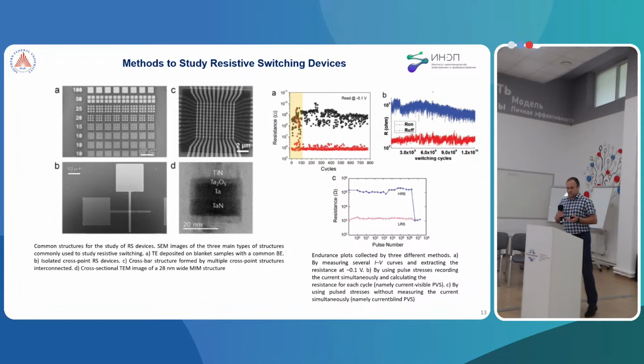There are some main electrical parameters which are used in investigation of memristive structures. This is the resistance, and we use different tests for investigation. The first test is an endurance test, which plot is collected by three different methods. By measuring several current-voltage characteristic curves and extracting the resistance at a common voltage; by using pulses, stress recording the currents simultaneously and calculating the resistance from each cycle; and by using pulse stresses without measuring the current.